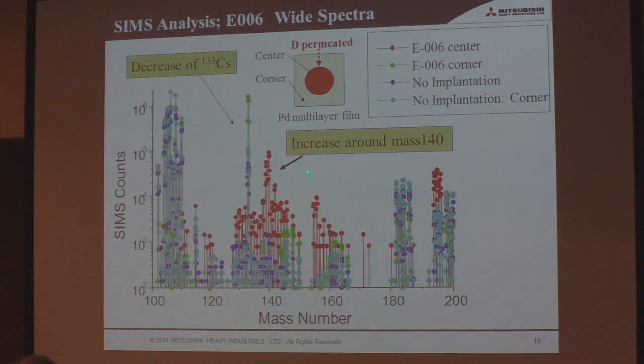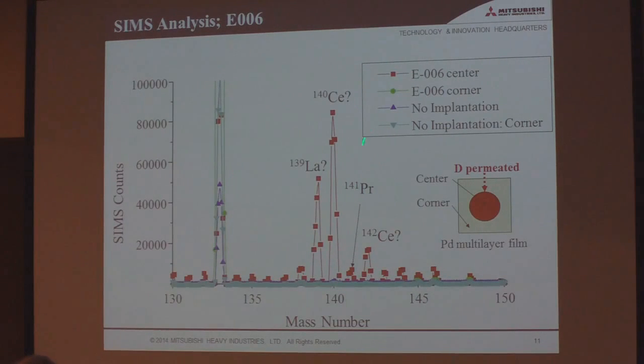And if we enlarge this spectrum, we can see the center and corner here. Only at the center can we see the mass increase at 139, 140, and 141, and cerium 142. And this analysis is performed by SIMS, secondary ion mass spectrometry.